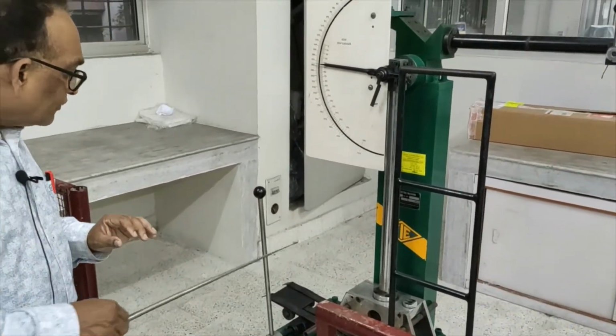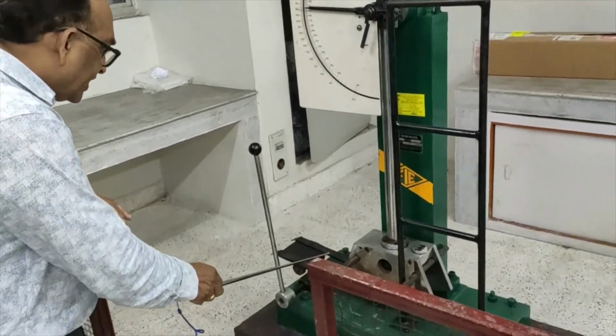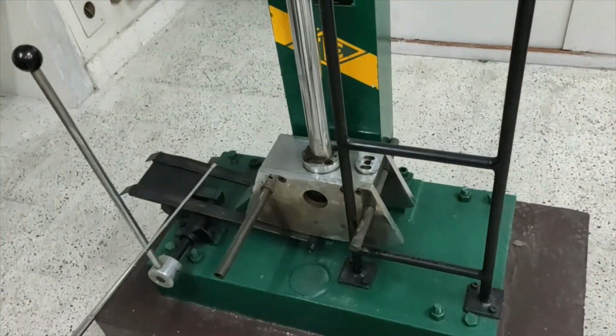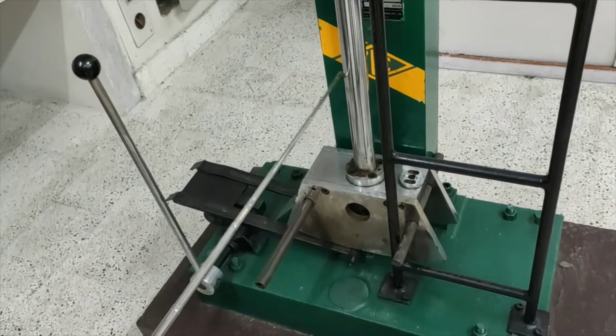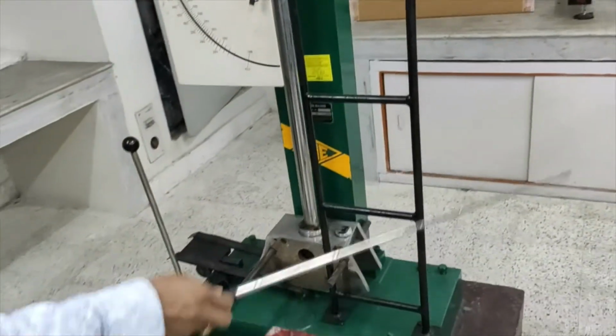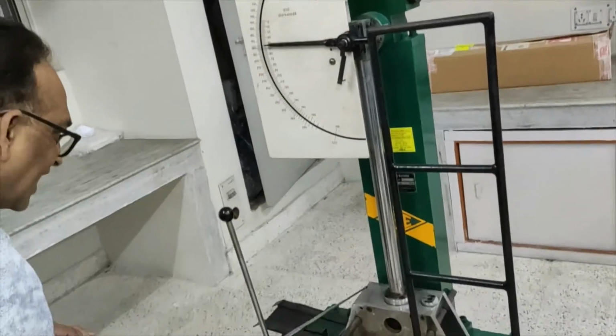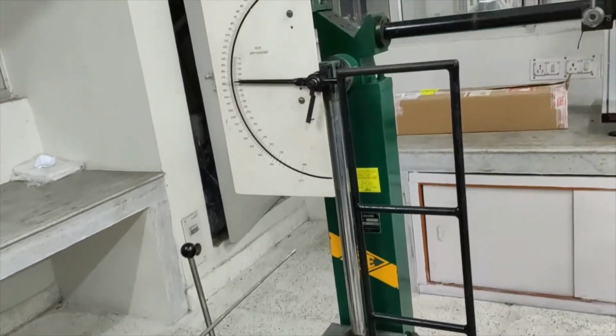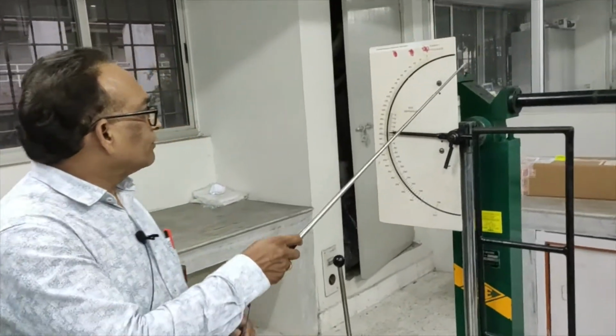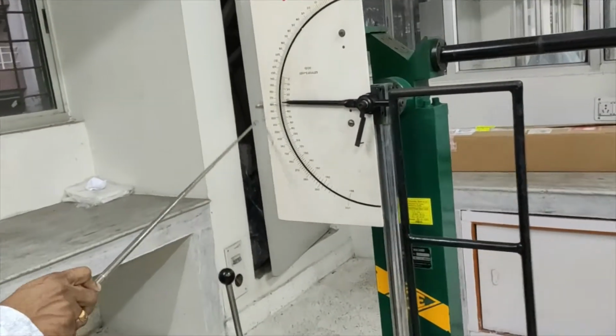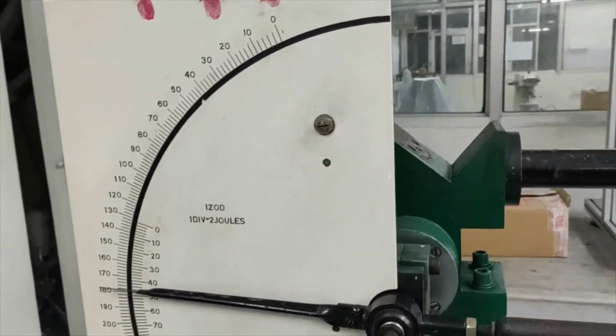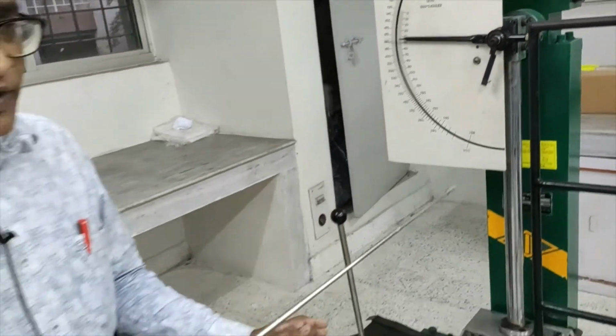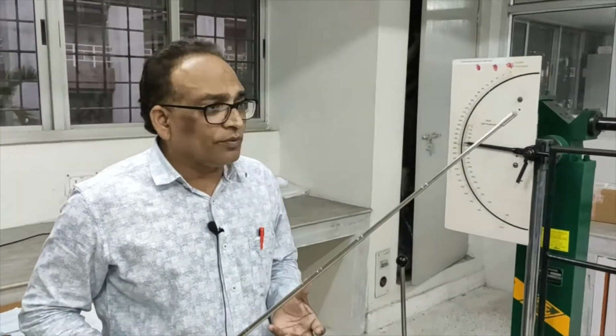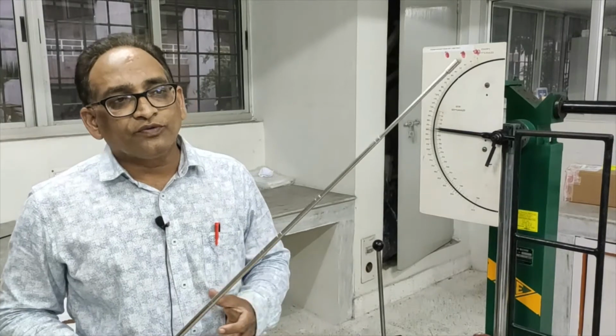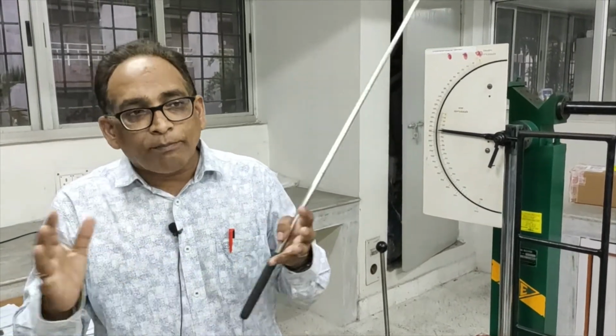So what we do is keep the specimen over here in this location in the Izod and Charpy test, then bring this hammer to this position and release it in free air. The hammer comes and hits the specimen, and the specimen breaks into two pieces, and from this scale we can measure the amount of energy absorbed until the fracture, and that gives the value of the toughness of the material. And it is extremely useful for comparing materials.